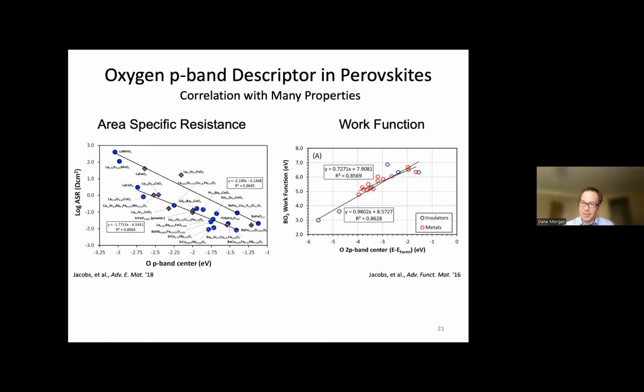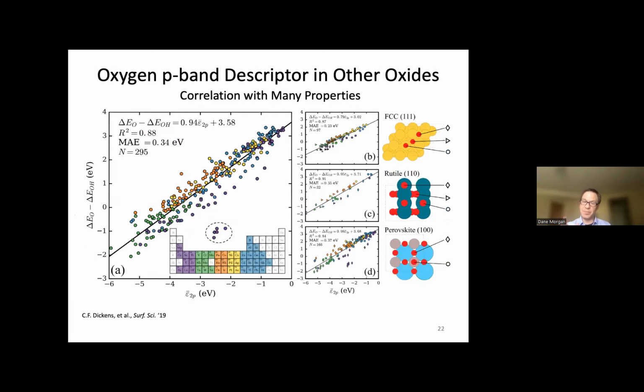And even other properties that really have nothing to do with oxygen transport, but we've just been intrigued to realize correlate with this p-band center. Work function of perovskite oxides correlates with p-band center. This is calculations of a bunch of different work functions of a number of different oxides. And we found a pretty good linear correlation with work function, with p-band center. And it's important also that a result is usable by some other group besides your own. Those are all examples that we found.